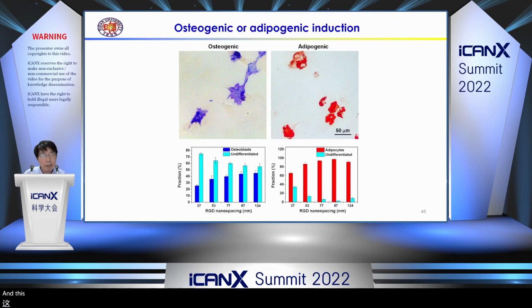And this is much more difficult because to examine the cell differentiation, you must keep the background non-fouling for quite a long time. But anyway, we found that both the osteogenic differentiation and adipogenic differentiation can be adjusted by the RGD nanospacing. What is more interesting is that with the increased RGD nanospacing, although the cell spreading area will be decreased.